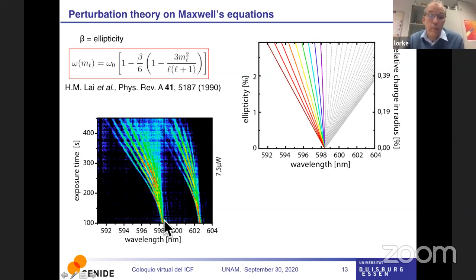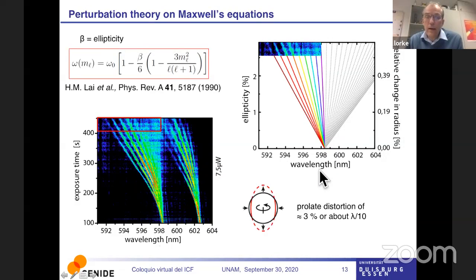We also know from the spectroscopy that I had shown you before what the L is. And in this case, I think it's 35. So we know that in principle, it should fan out into 35 different resonances. But you don't see the other side here. That's why I grayed this out. But you can take what we see and adjust it until it fits with our data. And then you get that indeed, this can be explained by a prolate distortion of these spheres by only 3% or about lambda over 10.